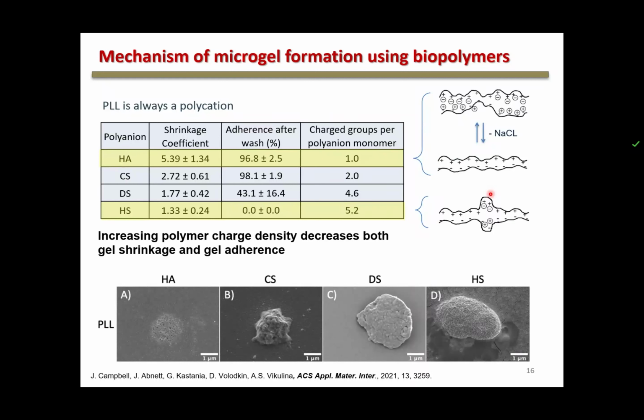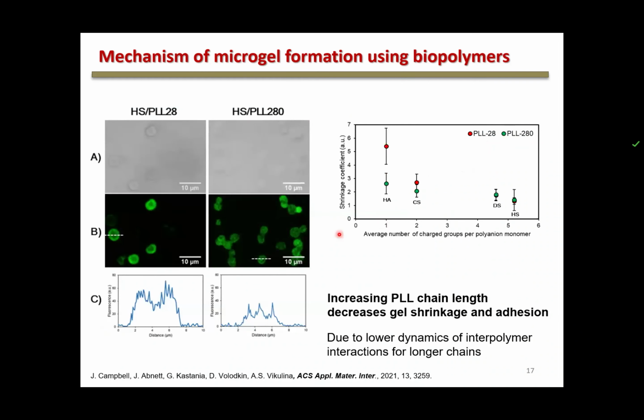We did not succeed to get rid of it at very harsh conditions unless you want to mechanically scratch it out. So just some interesting observation. If you increase the polymer chain, in this case we just used polylysine of 28 on average or 280 kilodalton. So if you make the polymer longer, then it suppresses both the shrinkage and adhesion.